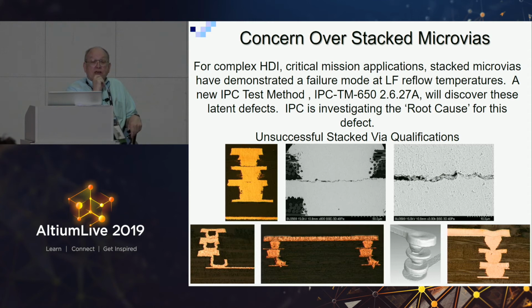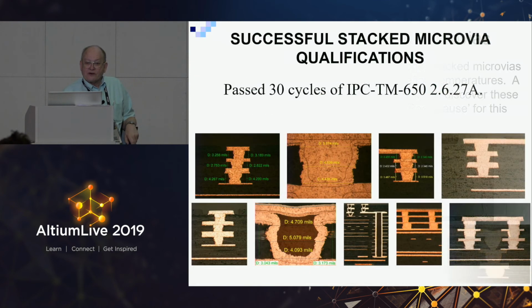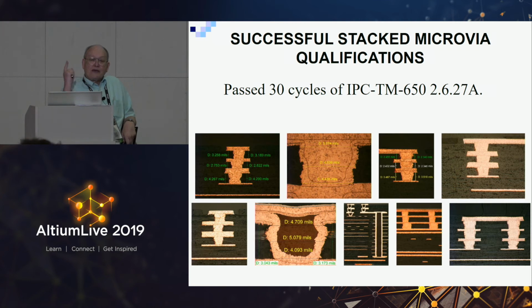And if you want, you can get a 60-page white paper that we put out on what the problem is, how it came about, how long we've been living with it for mission critical. And we're working with the European Space Agency right now on root causes, solutions, and simulations to figure out what's going on. But stacked microvias are right now a problem that we haven't quite figured out. Here are successful stacked microvia qualifications. These things pass 30 cycles of this IPC 2.6.27A. So we have some examples of 3-stack and 4-stack that did pass.